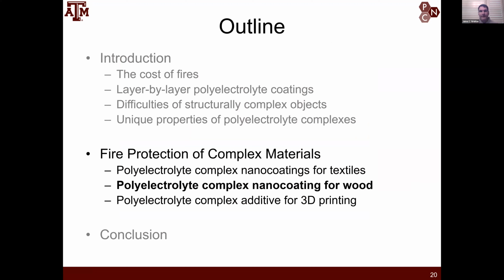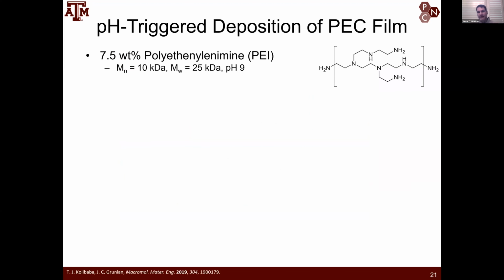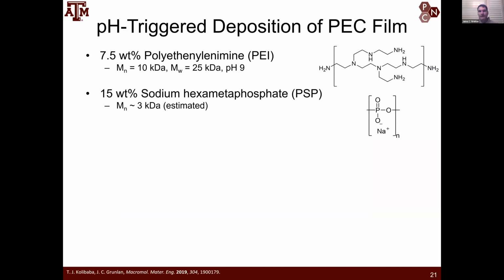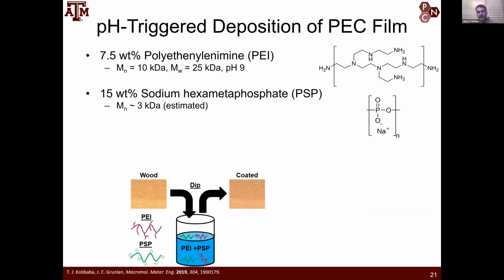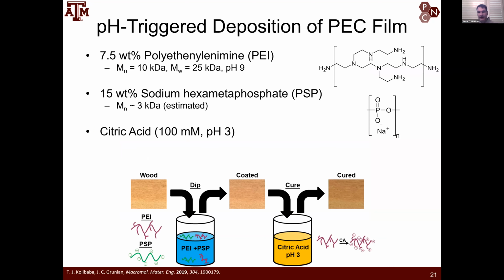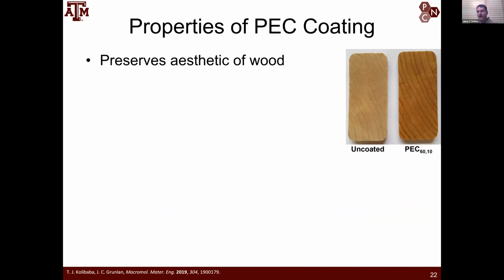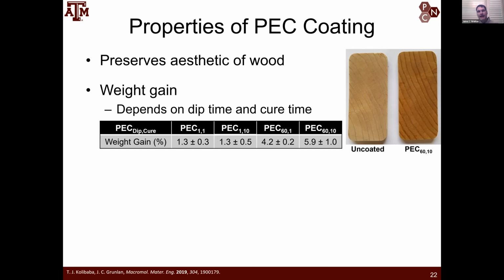I mentioned wood was hard to coat with layer by layer assembly, and so we used polyelectrolyte complex coating instead. Here's PEI, here's sodium hexametaphosphate. I've already introduced these molecules. And then what you can do is you can soak wood into this PEI PSP solution and cure it with this buffer treatment, just citric acid in this case, just like we did with the textile. And then you get a flame retardant wood created in this process. And so you can see that the coated wood maintains all the same aesthetics. You wouldn't know that there was a coating visually.